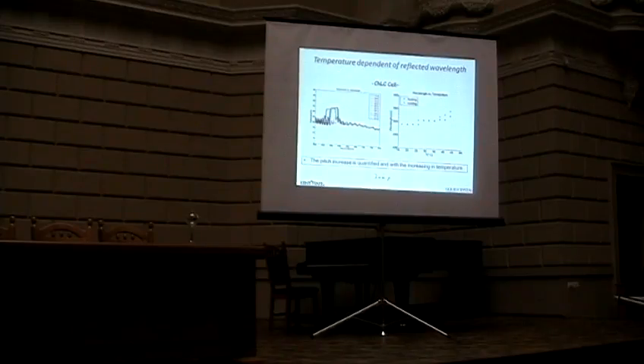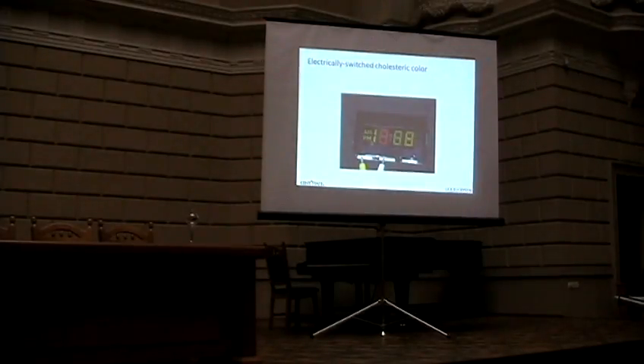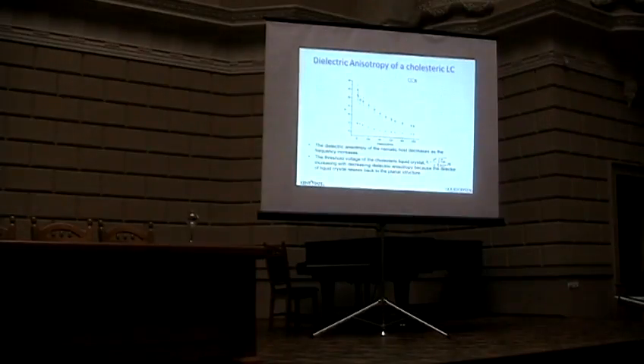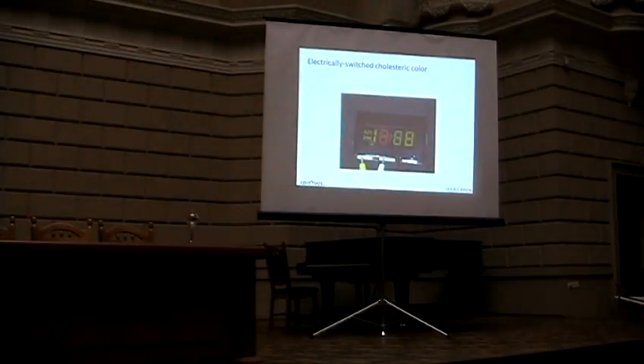With this type of material, the device becomes less temperature dependent, until the isotropic temperature of the cholesteric material, and then you lose this, and that's the switch of the device color. You can see just by applying the field, you can shift a little bit.